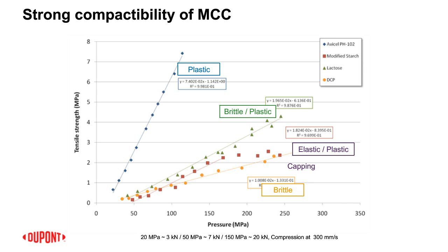Yeah, MCC is MCC, so it's always a plastic deformed material. The fundamental won't change. Of course, there's slight difference, right? For example, higher moisture will increase plasticity a little bit further. But fundamentally MCC is a plastic deformed material. So between different grades, it's the same chemistry and the same basic material property. It has similar critical material attributes. It's very different from other materials like dicalcium phosphate, lactose or starch. But there's slight difference within each grade.